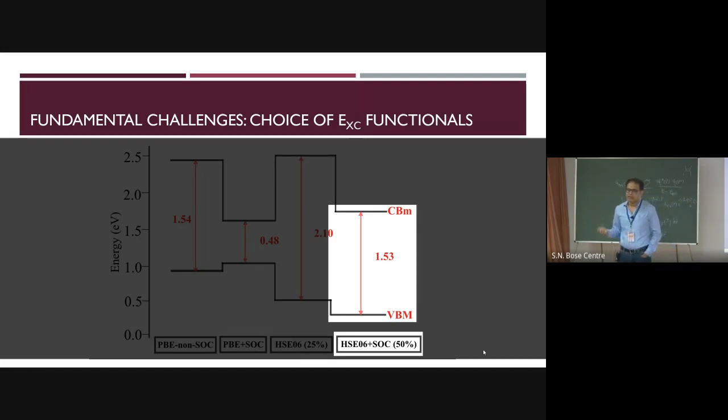That means if you are trying to understand the stability or the exciton or other things, these levels make much more sense compared to these. Would you align it? What is the reference? Reference means, so these are all offset, right? So you have to put something with respect to some reference, typically with respect to vacuum. So there's a surface, yes, and you have to align it to the vacuum levels. Once you calculate the work function, you basically take a graph and then you align. That's the idea.